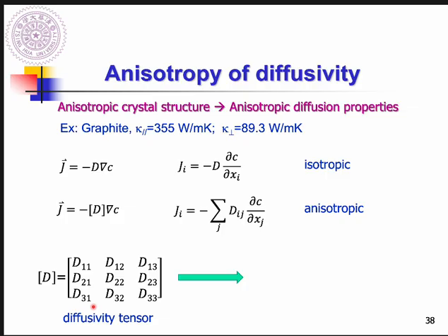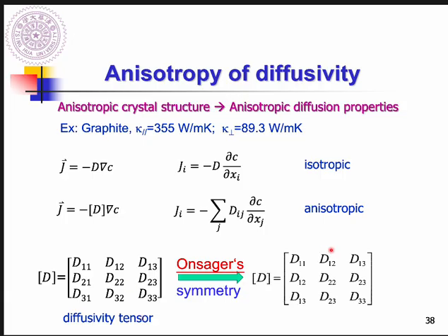we want to talk more about the diffusivity tensor. This is a 3 × 3, so some people probably will think we have 9 unknown parameters for diffusivity. It's so complicated. So based on the symmetry, you can reduce the unknown parameters from 9 to 6. We will assume D21 equals D12, so we use D12 to represent both.